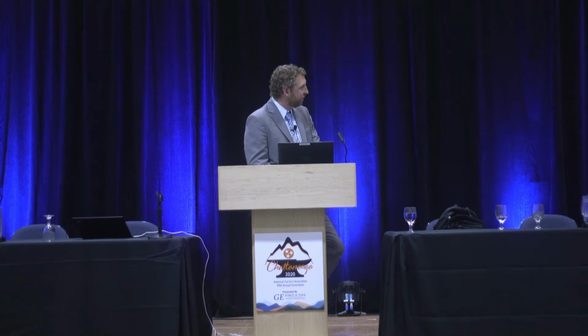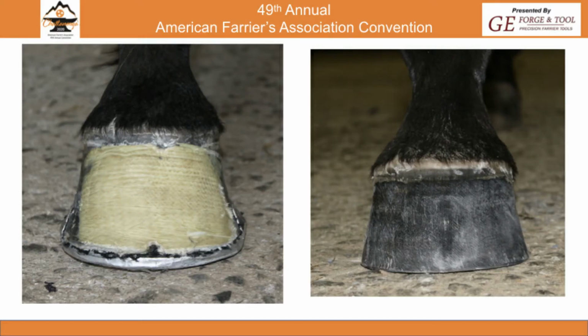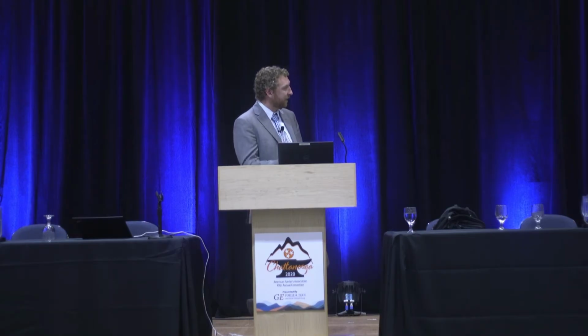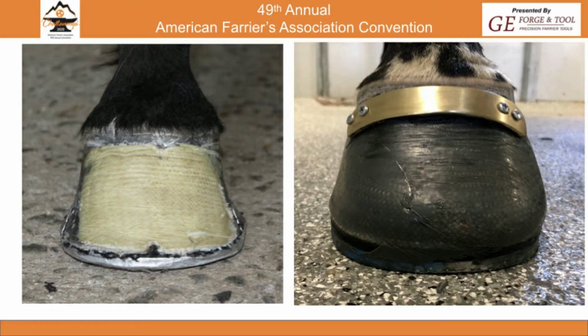And so I often found that patches even like this, with multiple layers all the way top to bottom, would still recrack. So I found myself with toe cracks, getting them to grow out, often having to do something like this: reinforce it with brass or aluminum or steel or something at the most proximal edge of it. And so naturally that's what prompted this study.